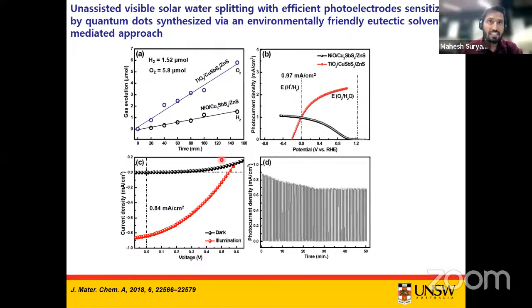You can see we initially measured the H2 and O2 evolution rates, which were found to be about 1.52 micromole for H2 and about 5.8 micromole for O2. Of course, there are a few discrepancies in the values because we measured H2 separately for the photocathode and O2 separately for the photoanode.